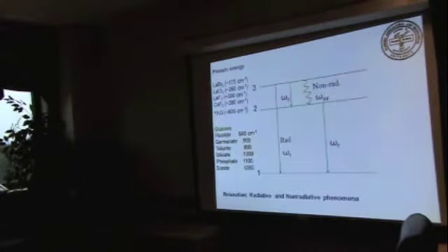If this energy gap is, let's say, maybe 3000 wave numbers, in a sodium borate host, the phonon frequency is 1350, then you need a little more than 2 phonons to fill the gap. Then it becomes 3 phonon relaxation, or when the number of phonons increases, you say multi-phonon relaxation. That's the phenomenon that happens between these energy levels. So this is called non-radiative relaxation. That means no light comes out.